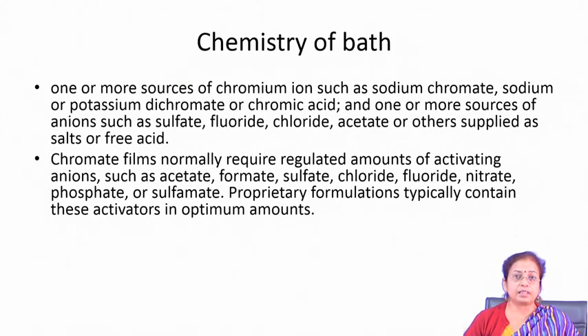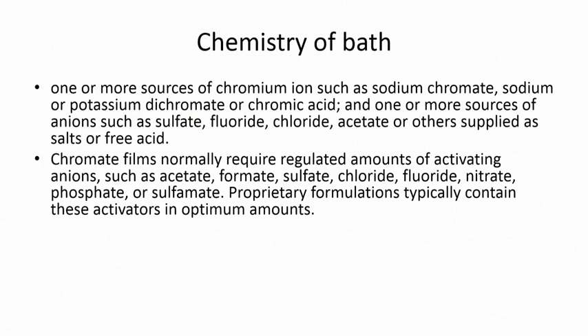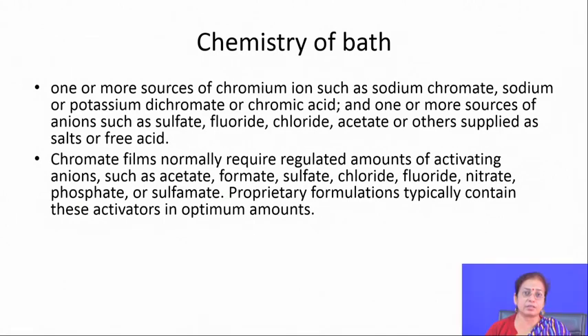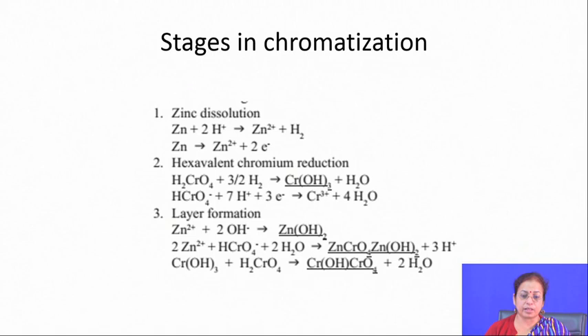So, usually one or more sources of chromium are used, such as sodium chromate, sodium or potassium dichromate, and one or more sources of anions such as sulphate, fluoride. These are used as ingredients for the solution where you are doing chromate conversion coating, and it normally requires regulated amount of activating anions such as acetate, formate, sulphate, and proprietary formulations typically contain these activators in optimum amount.